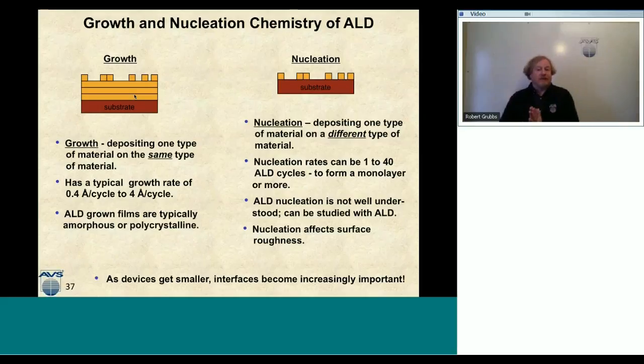So now let's talk about nucleation. Nucleation is depositing one material on a different type of material. So that different type of material may not have these nice hydroxyl groups to nucleate on. It'll have a different chemical structure. It'll have a different electronic structure. So how chemistry nucleates on those surfaces is going to be very different than growth. And so if you study nucleation in ALD, it'll tell you that there's very dramatic differences between nucleation chemistry and growth chemistry. So nucleation rates, or the number of cycles it takes to actually nucleate an atomic layer film on top of a film, can be up to 1 to 40 ALD cycles, just to form that initial ALD monolayer where growth can take place.